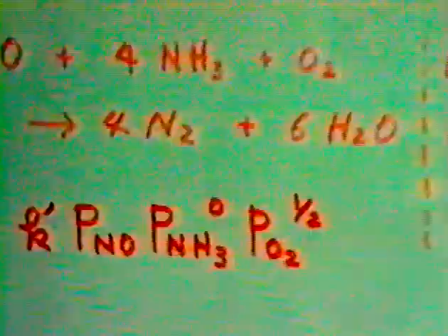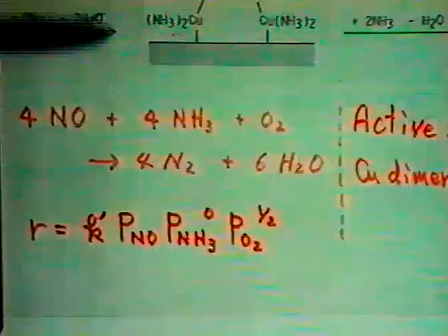From the results obtained here, we propose the structure of active sites of Cu-zeolite catalyst for the selective catalytic reduction of nitric oxide with ammonia. In the case of high silica zeolite, such as ZSM-5 and mordenite, Cu2+ is introduced into the zeolite as a form of CuOH+ because the cation exchange sites are separated far from each other. When the surface CuOH+ concentration is high, this kind of copper dimer may be formed by dehydration at high temperature. We think this kind of copper dimer is highly active.